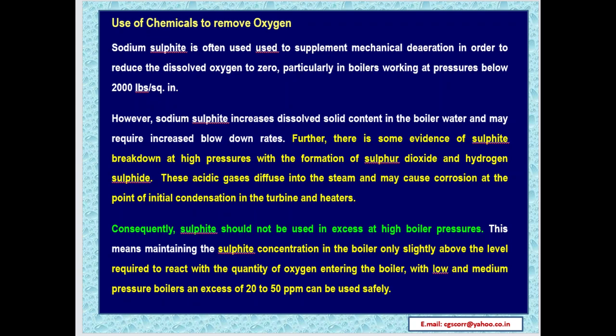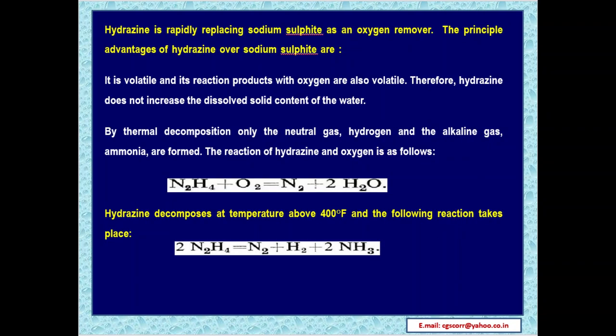Consequently, sulphite should not be used in excess at high boiler pressures. This means maintaining the sulphite concentration in the boiler only slightly above the level required to react with the quantity of oxygen entering the boiler. With low and medium pressure boilers, an excess of 20 to 50 ppm can be used safely. Hydrazine is rapidly replacing sodium sulphite as oxygen remover. The principal advantages of hydrazine over sodium sulphite are it is volatile and its reaction products with oxygen are also volatile. Therefore, hydrazine does not increase the dissolved solid content of the water.